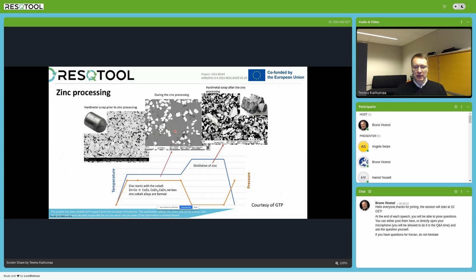And once the temperature is increased and pressure is decreased, zinc starts to boil and is evaporated, and the evaporation of the zinc from this alloy creates then empty space, like seen here in the right picture. And that means that the part has a lot of porosity and is very fragile, can be easily ground to powder form after cooling of the furnace.